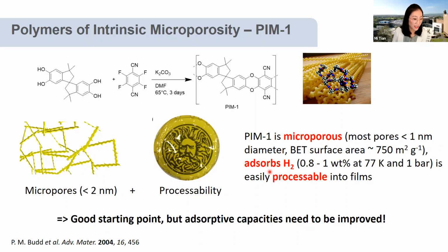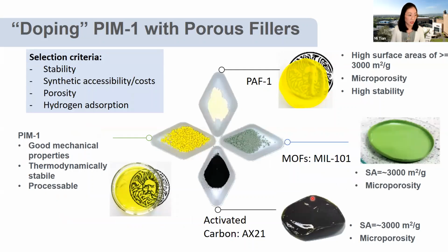That ticks our box, and it's easy to process into films. However, the hydrogen storage capacity is relatively low, less than 1%. So this is a good starting point, but the adsorptive capability needs to be improved. To improve its storage capacity, we doped the PIM-1 with porous fillers. This is PIM-1 granules. It can be dissolved into organic solvent and then cast into a transparent yellow film. Those are porous fillers with extra high surface area and hydrogen storage capacities. The only problem is that they are in powder form and not processable. So the composite membrane combines the good processability with the high hydrogen storage capacity from the fillers.